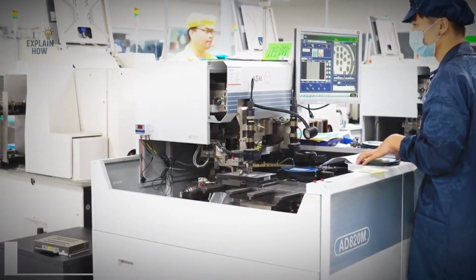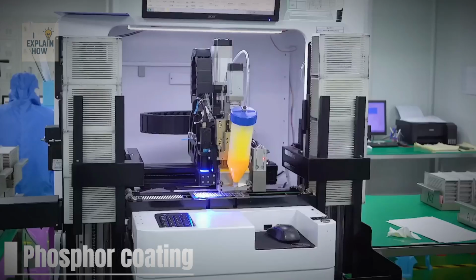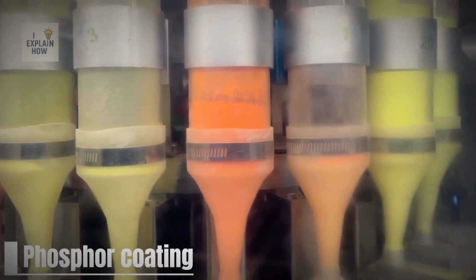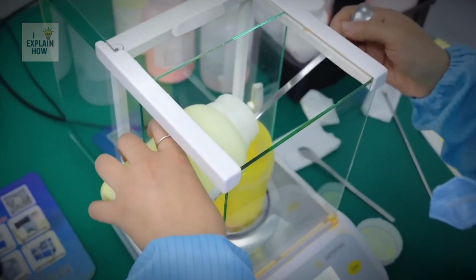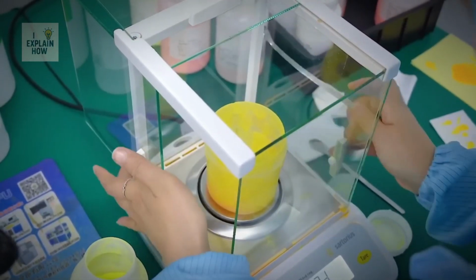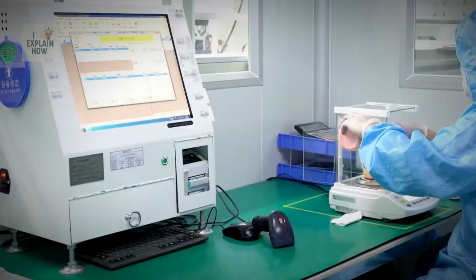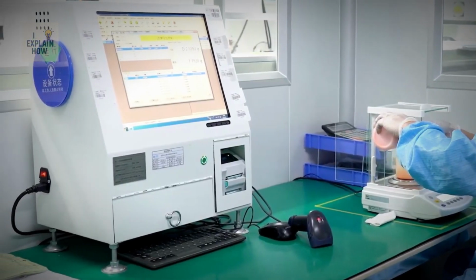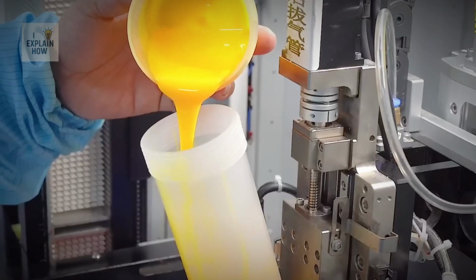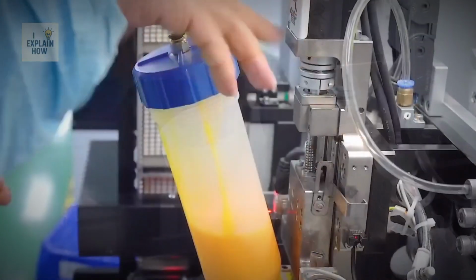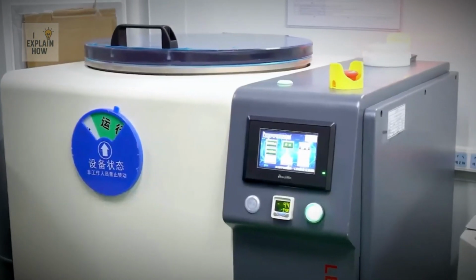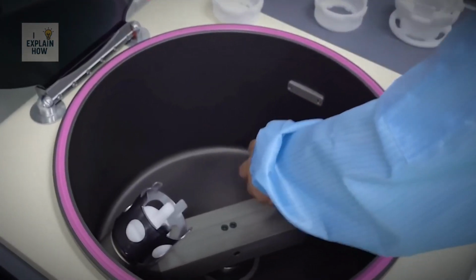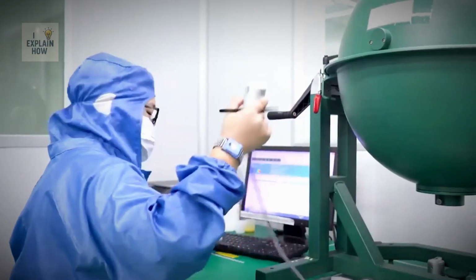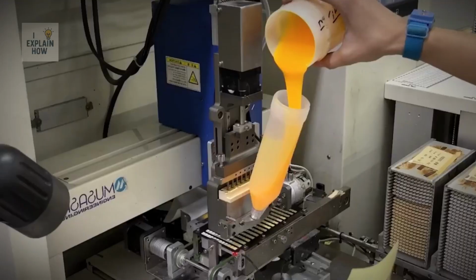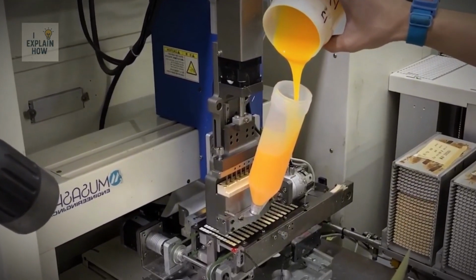Once gold wire bonding and initial inspection are completed, the LED frames are transferred to the phosphor coating area. Raw phosphor powder is first weighed using an analytical balance with 0.0001 gram precision. According to the target color temperature, engineers mix several phosphor powders, yellow, orange, pink, and other spectral modifiers, according to precisely calculated ratios. After weighing, the mixture is sent to a high-speed mixer where the phosphor powder is uniformly dispersed throughout the epoxy solution. Then, the phosphor epoxy mixture is loaded into the dispensing cylinder of a phosphor dotting machine.